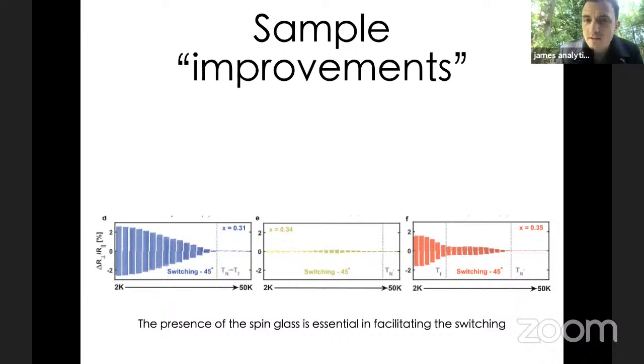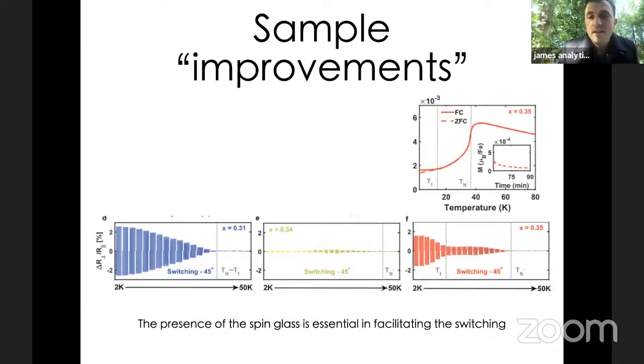And then we tried the sample with the sharpest heat capacity anomaly, with the sharpest magnetization transition, and looked at its antiferromagnetic switching. And what you see is basically a null signal. In other words, even though the sample is more perfect, to use an American expression, the system doesn't seem to switch really at all. Let's go back to the magnetization and try and figure out what's going on, particularly with the sample here.